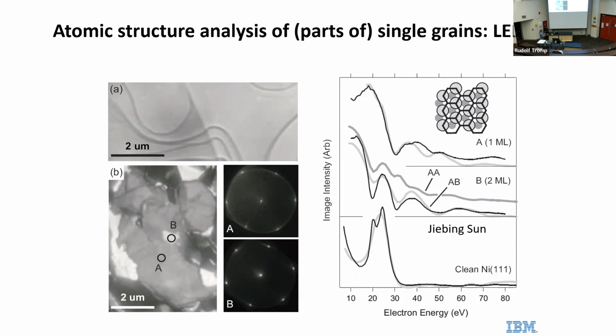And we see this spectrum has really changed rather dramatically. And this small area B here, where we have two monolayers of graphene, right? And you see again, well, this is one monolayer of graphene, this is two monolayers of graphene. You see the spectra are all very different. Now, if you put in the atomic structure, you can calculate what you expect. And so for clean nickel, it looks very much like the experiment.